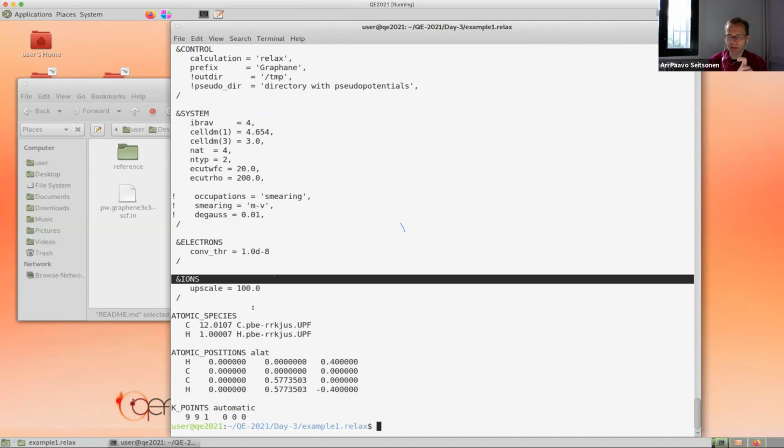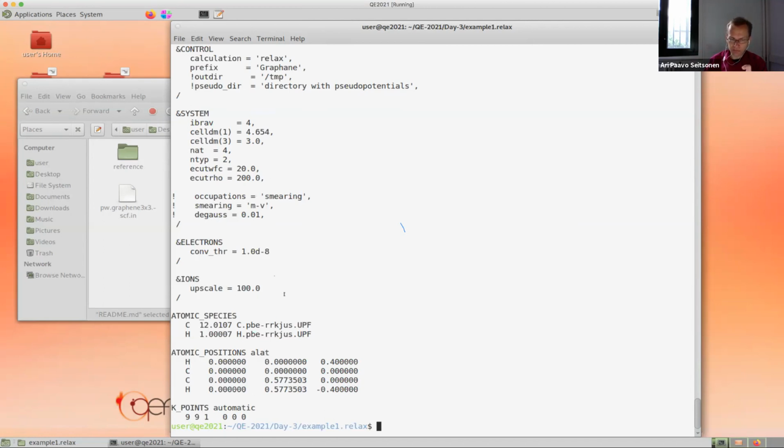What I do sometimes is also reinitialize the forces and the history of BFGS. So I just copy the coordinates into a new input file without doing a restart. Because if you do a restart in the control section, normally it also restarts with the history of the relaxation. What I do is start from zero. This forgets the history. I don't know if that was clear.